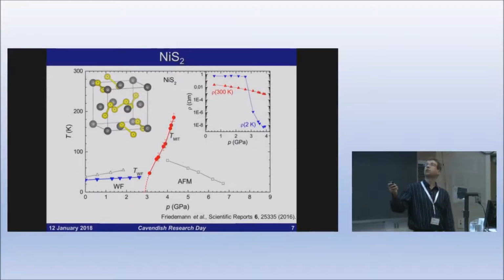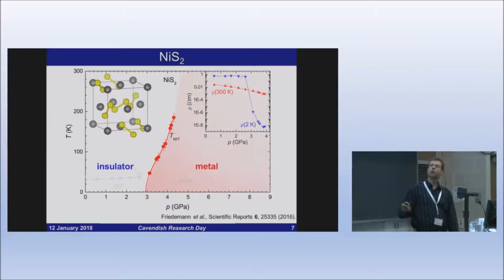Now, the same is true for what I'll be talking about today, which is our work on nickel disulfide. You can see the structure here with sulfur atoms in yellow and nickel in gray. This is the phase diagram, as a function of temperature and pressure. There are quite a few lines of magnetic order we see, but if we ignore those for the moment, just focus on the metal to insulator transition. At zero pressure and at low pressure, this material is an insulator. And as we apply a fairly large pressure, about 30 kilobar, we enter a metal. We turn the system from an insulator to a metal.